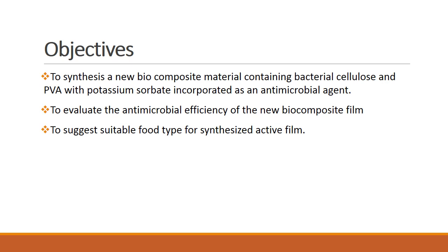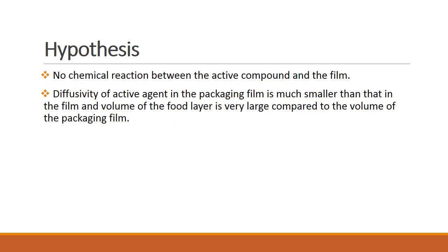for the synthesized active film. The hypothesis of my research project is that I assume there is no chemical reaction between the active compound and the film. Also, the mechanism is through diffusion. Therefore, the diffusivity of the active agent in the packaging film is assumed to be much smaller than that in the food, and the volume of the food layer is very large compared to the volume of the packaging film.